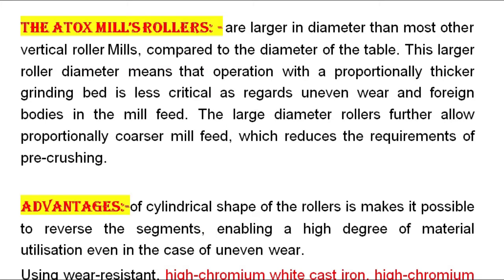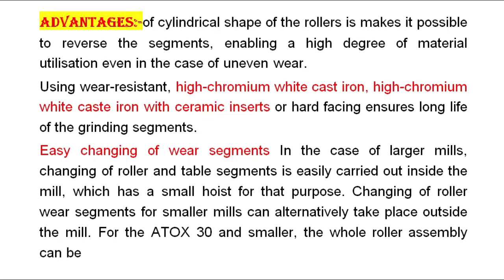Atox mill rollers are larger in diameter than most other vertical roller mills, compared to the diameter of the table. This larger roller diameter means that operation with a proportionally thicker grinding bed is less critical as regards uneven wear and foreign bodies in the mill feed. The large diameter rollers further allow proportionally coarser mill feed, which reduces the requirement of pre-crushing. An advantage of this cylindrical shape of rollers is that it is possible to reverse the segments, enabling a high degree of material utilization even in case of uneven wear. Using wear resistant high chrome white cast iron with ceramic inserts or hard facing ensures long life of the grinding segments. Easy changing of wear segments in case of large mills.